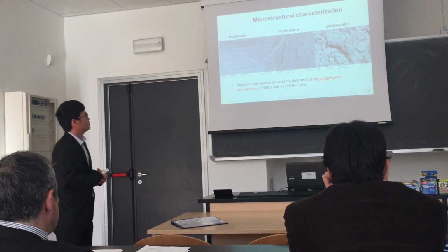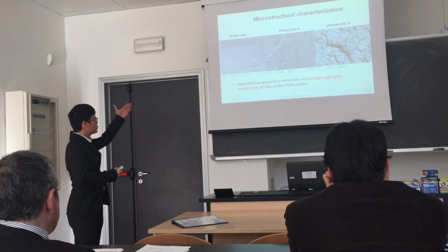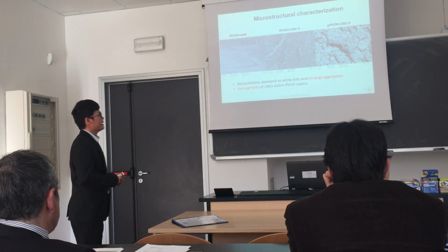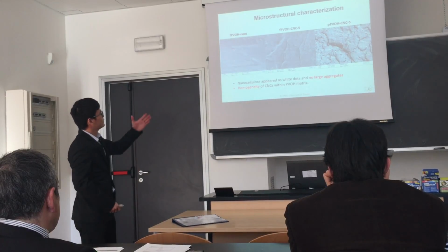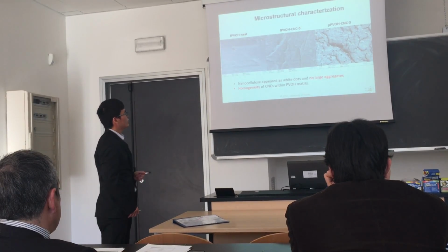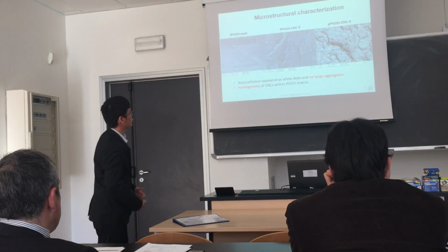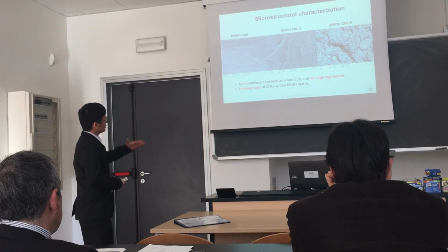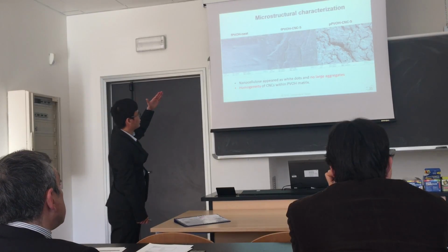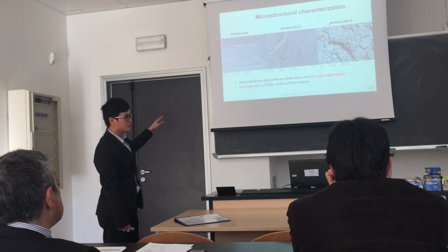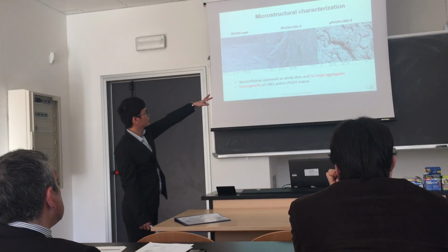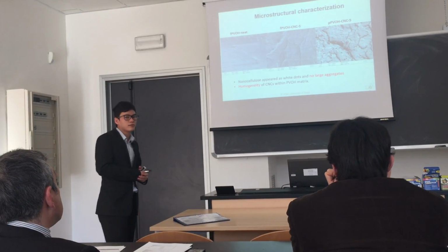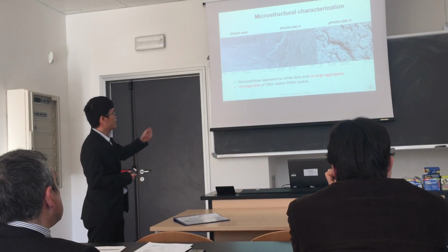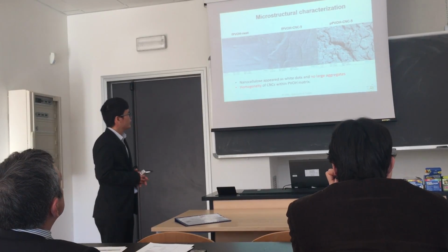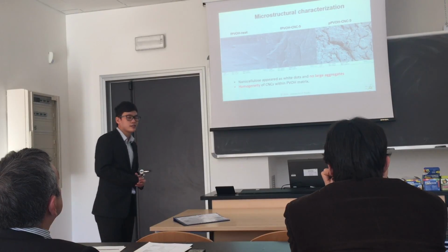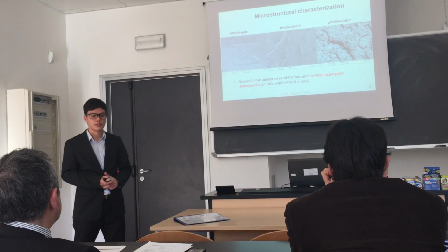And here are the results of the microstructure characterization. From the left to the right, we can see the SEM micrographs of the neat filament, the composition with 5% in filaments, and the composition with 5% in the 3D printed sample. So we can clearly see that in the pure neat filament, the surface is very smooth, whereas the surface in the composite is a little bit rough due to the presence of the nanocellulose. And nanocellulose appears as white dots, and there were no large aggregates. And the observation revealed the homogeneity of the nanocellulose within the PVDF matrix.